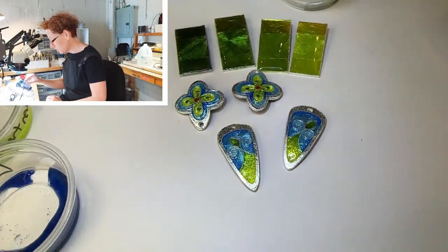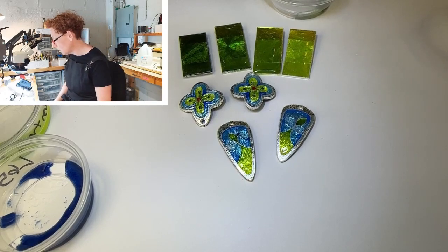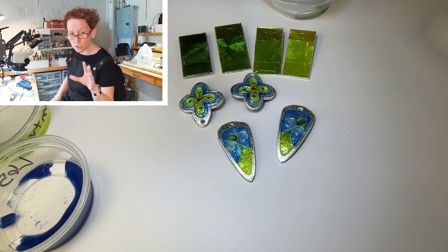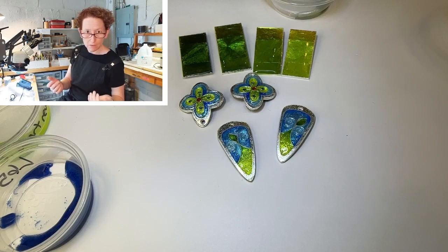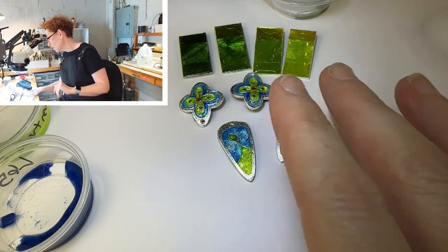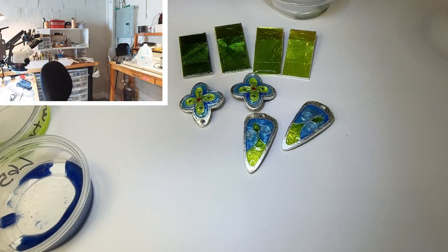Let me zoom out just a little bit because we're going to do some Soyer N4 on the top of these. Because you know what? There's that finishing flux, 676 finishing flux, which is supposedly the match set for the Soyer number 3. I don't like it, that's all I'm going to say. I think it's a little too reactive to silver. So that's why we're going to use N3, N4. N3, N4 are the same thing.